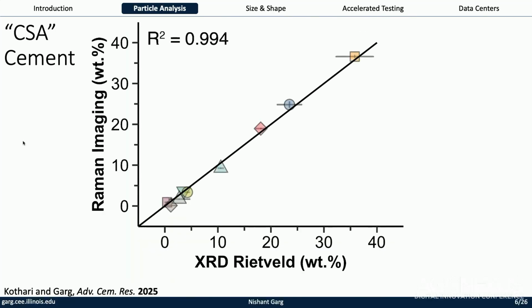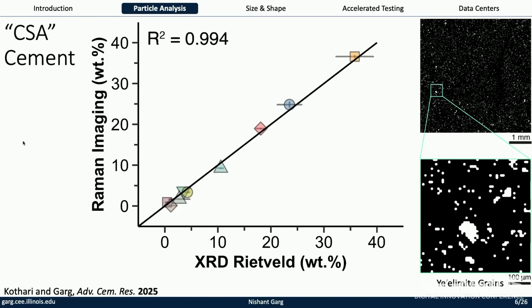Right? So in this particular case, we are now starting to see the first images of this phase called ye'elimite in calcium sulfoaluminate cements, or you may know them as type K or expansive cements. This sets very, very fast. In a few minutes, you get very high strength, what you would get in a few days. And it's coming from that phase called ye'elimite, which we can now see as individual grains at this level. Okay. So that's particle analysis.